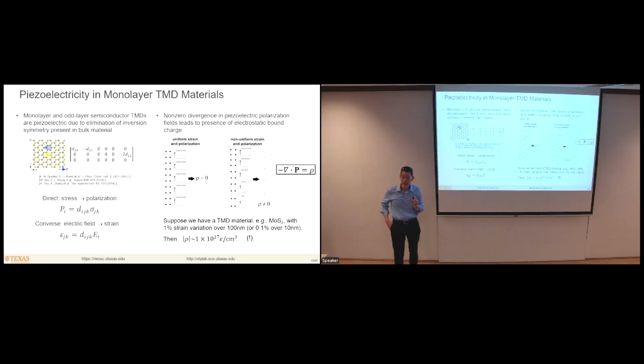However, if you have a monolayer, then you only have this, right? The structure then no longer has inversion symmetry, and the piezoelectric coefficients that you can get are non-zero and actually can be quite large, okay? And one of the things that is then very interesting is that if you have spatial variations in the piezoelectrically induced dielectric polarization, then you get corresponding bound charge, electrostatic bound charge densities in the material. All right, and more specifically, that bound charge density is given by the negative of the divergence of dielectric polarization.